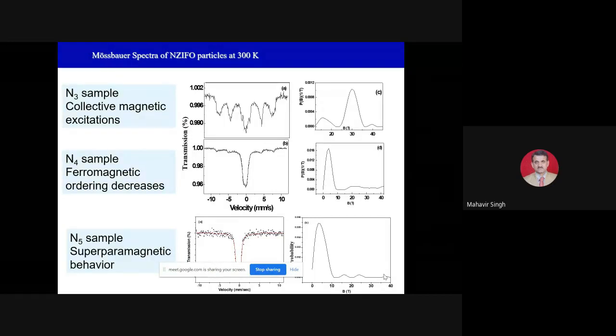Broadness means surface roughness. The same is the case in the Mössbauer distribution function, which we also fitted. In nano we have a broad Mössbauer peak, but in bulk we have a sharp one. So broadening means surface disorder. Dear friends, when we move from bulk to nano, surface disorder increases. That is why there is broadening of the peak at the nano level.